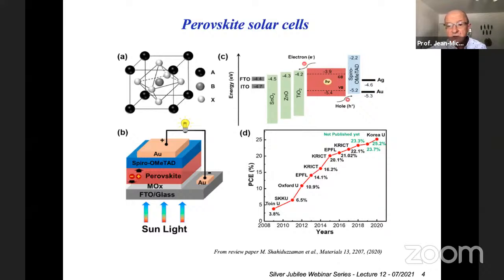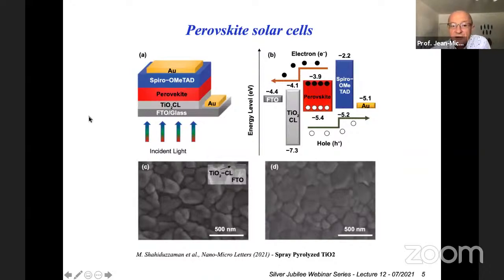For instance, we have been working on the bottom layer with colleagues in Kanazawa to optimize the deposition of the bottom layer, which often is a titanium dioxide layer for the collection and conduction of the electrons. So you can figure out with the diagram that the light is absorbed into the perovskite. This is a light absorber, which is situated below the hole conducting layer. And this is an energy diagram, and this is just the distance, which is a vertical distance through that device, which is pictured in the second picture, picture B.